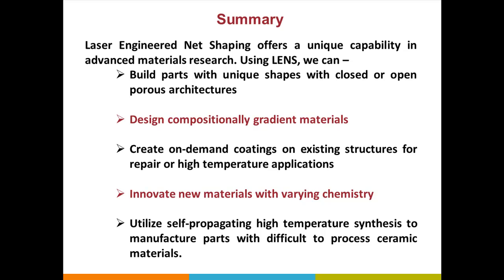The last thing I didn't touch on, but very recently we've shown that we can utilize self-propagating high temperature synthesis to make unique materials in LENS. A simple example: titanium diboride is very difficult to process, but using LENS we can feed titanium from one hopper and boron nitride from the other, and as we process, we create the reaction and make titanium diboride or titanium nitride coatings on top of the sample surface. These things are almost impossible to do using any standard manufacturing techniques.